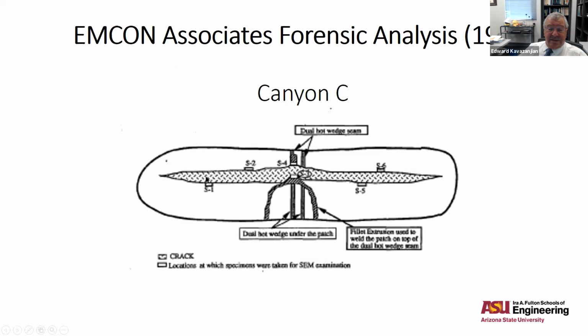If we look at Canyon C, this is where we had the lap weld. That tear occurred again right at a point where we had a fusion seam, but then we had a lap seam and we had a dual wedge seam under the patch. We had an extrusion seam on the patch. So we had a combination here of different types of seams, which led to strain concentrations.